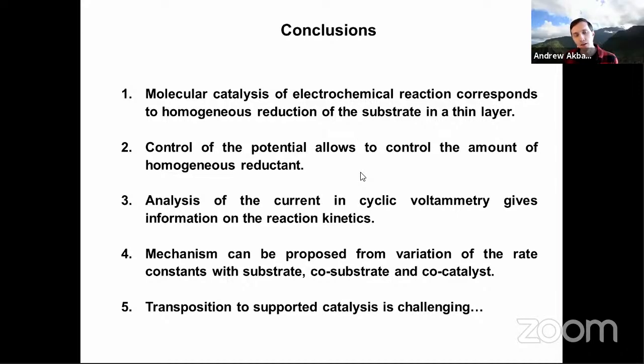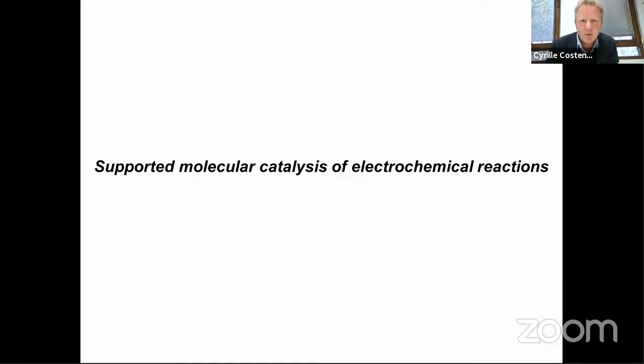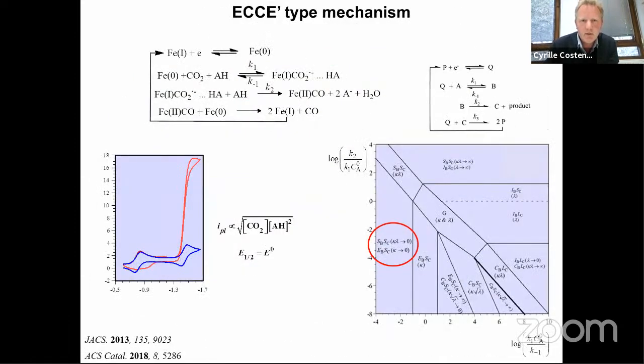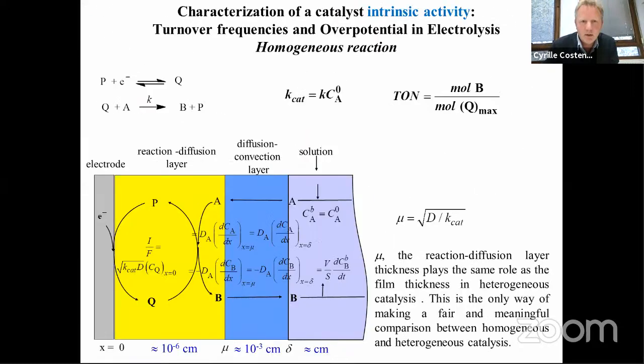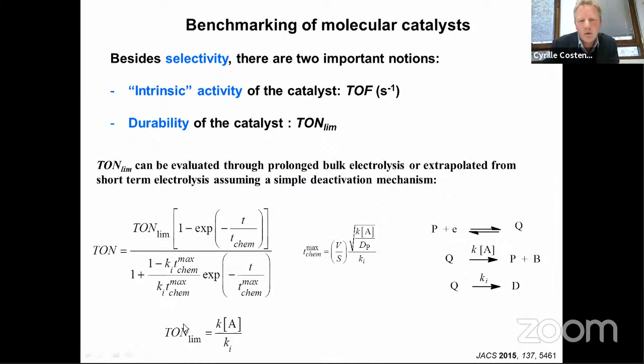So would it be better to fundamentally view the lifetime of the activated molecule rather than the turnover number before it gets destroyed? Yes. This is what I tried to show, but it was quite quick. Here, if you determine the maximal turnover number for a very simple system like this, you can see that this value depends on the lifetime of the catalyst, if you have a decomposition process of the catalyst. And it's the same if you do photocatalysis, for example, you have exactly the same problems.